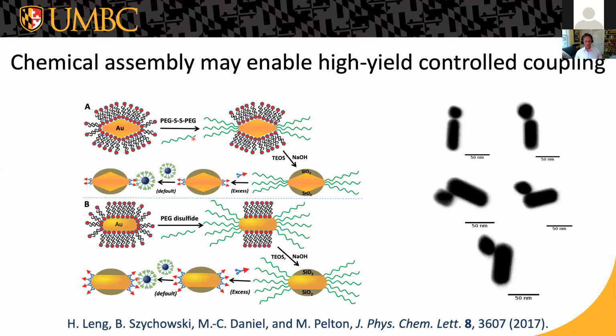functionalize the ends of these things, link them to the quantum dots in such a way that we end up with a high yield of three-particle chains: the metal nanoparticle, quantum dot, and metal nanoparticle, with the quantum dot located right where the field is going to be the highest between the two of them, and really have a macroscopic number of these strongly coupled systems that we can then study further or incorporate into devices.